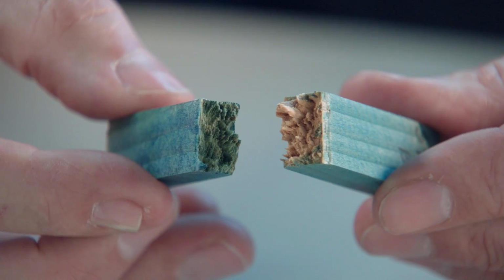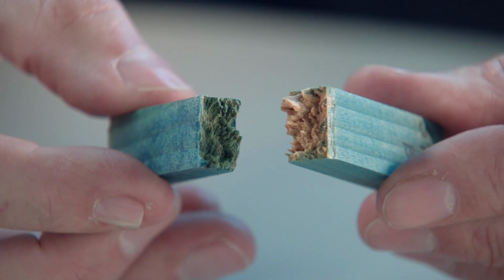Large particles cannot readily penetrate the wood of our native tree species. And therefore it was assumed that the smaller the particle, the better the copper preservative can actually penetrate the wood, and then we have a higher retention and better distribution in the wood. So you've been looking at how effective copper nanoparticle-based preservatives are. What did you find? Well, I found them to be comparable with conventional copper-based wood preservatives.